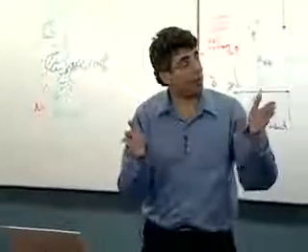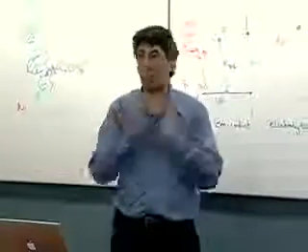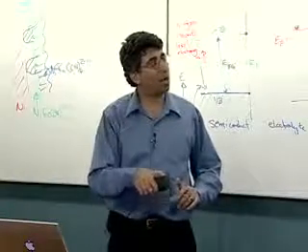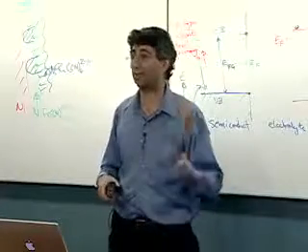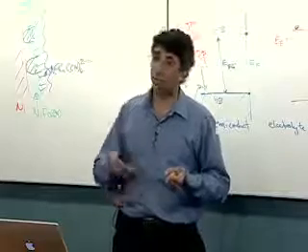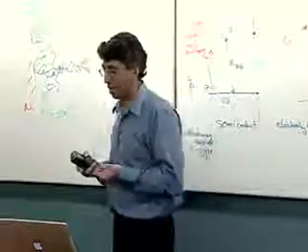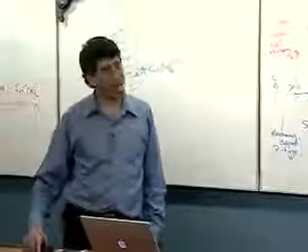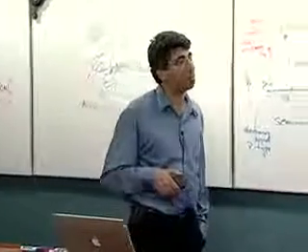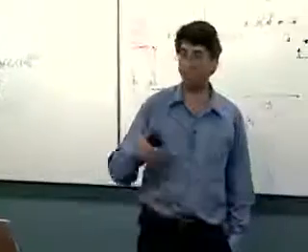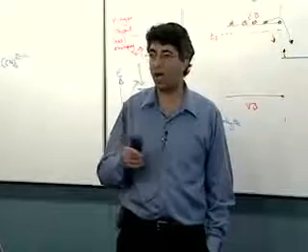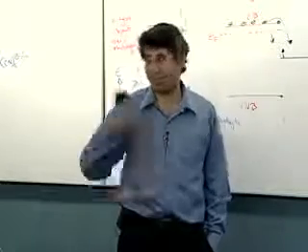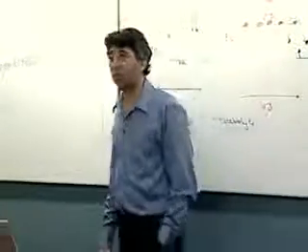On the other hand, if you go to a smaller band gap semiconductor, such as the gallium phosphide here, you start to run into problems where the semiconductor photodecomposes. And so you're limited in intensity, but even that will eventually become problematic. So one has to come up with chemical schemes that shut off the rate constants for photodecomposition while allowing the useful chemistry, such as hydrogen evolution, to continue.